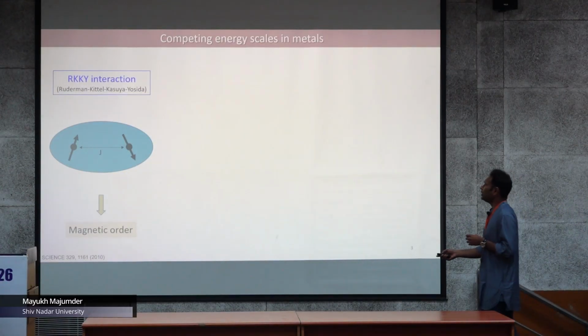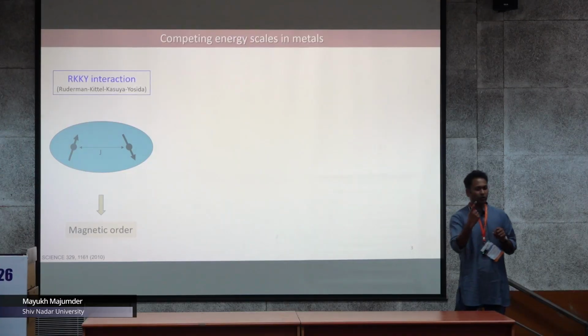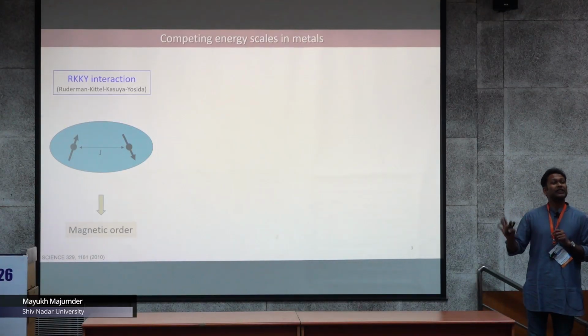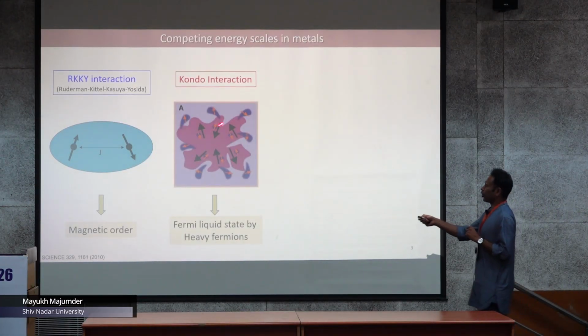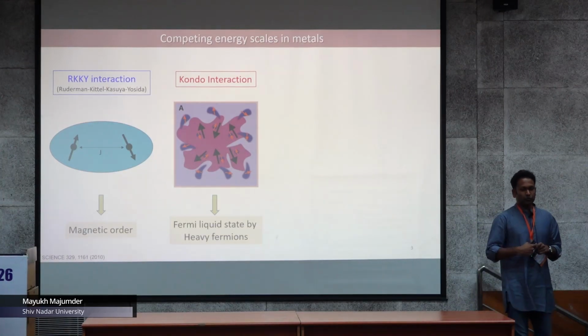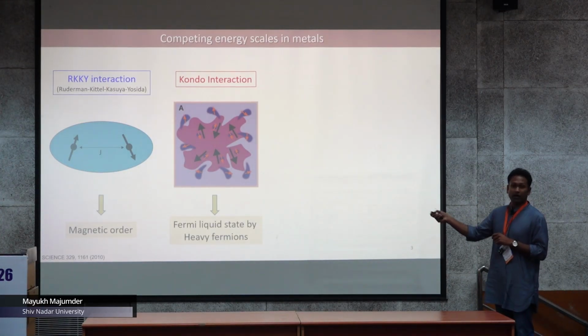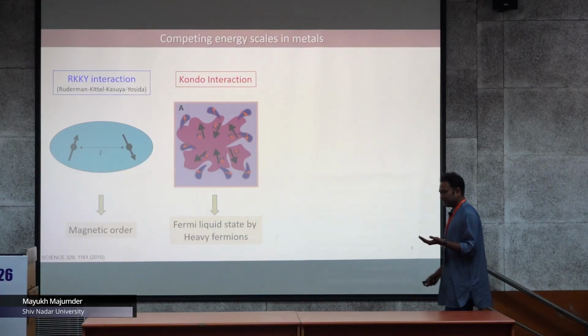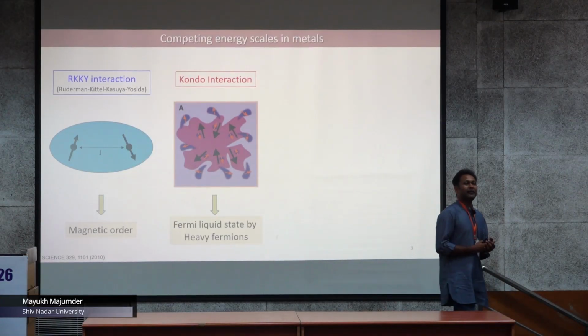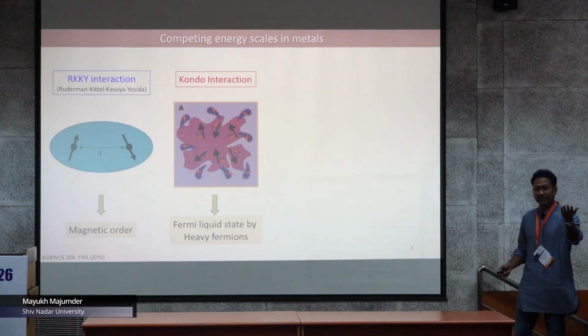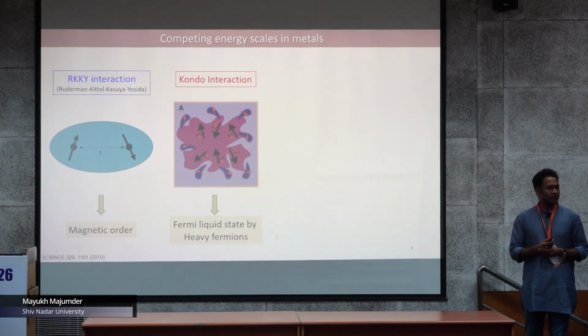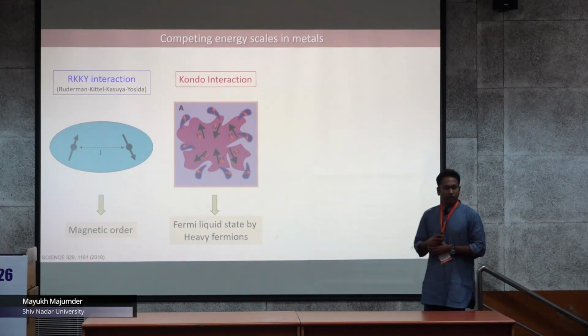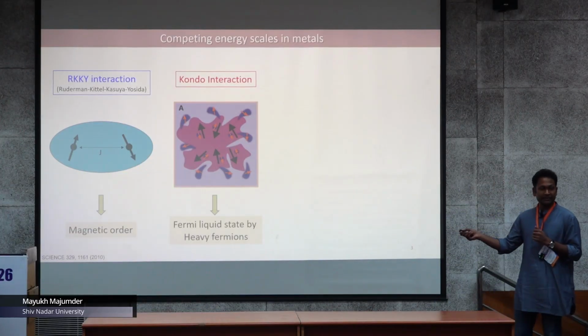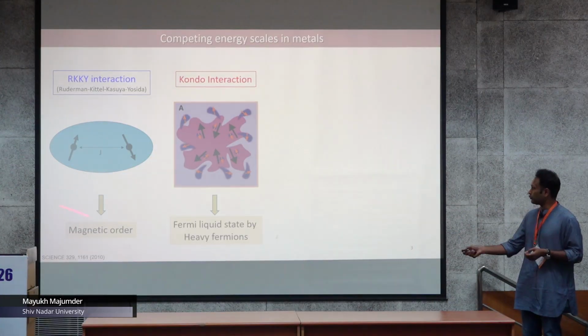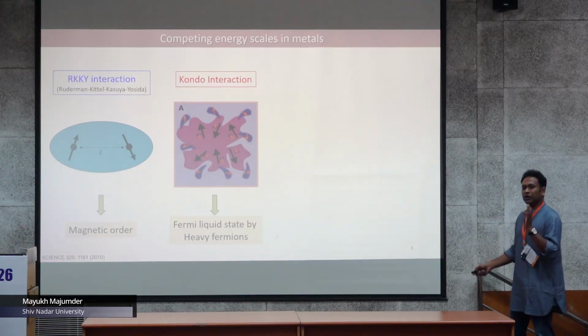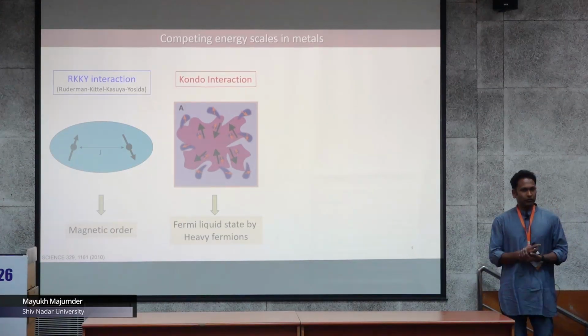Okay. Now, of course, if this J, the coupling between the local moment and the conduction electron, is sufficiently high, then the conduction electron tries to produce a many-body singlet state with the local moments. Because of that, the magnetic moment of the 4f element is screened, and that may give rise to a Fermi liquid-like state where there is no long-range magnetic ordering. So probably you have realized that these two interactions are competing with each other, right? One promotes magnetic ordering, another tries to suppress the moment of 4f, right?